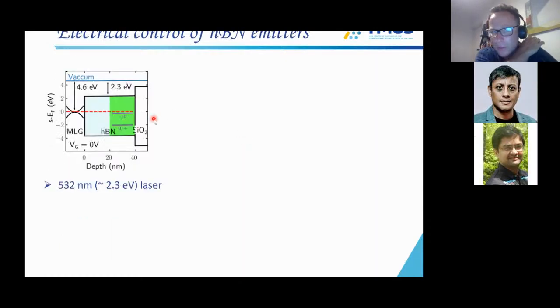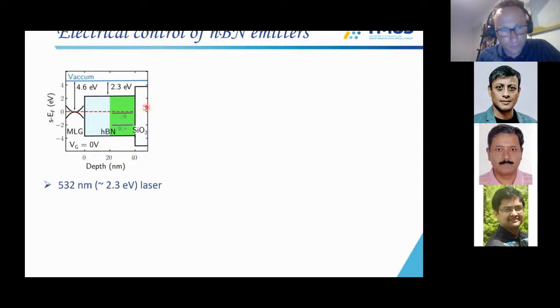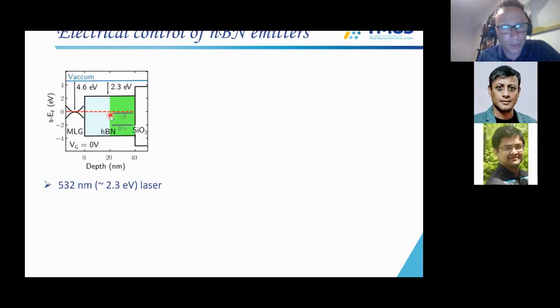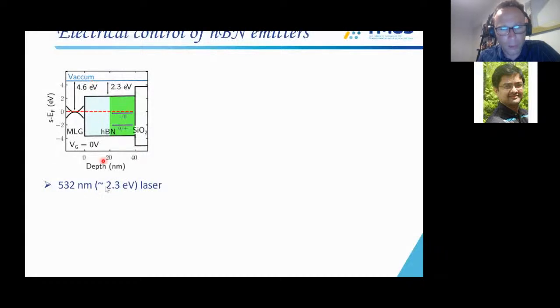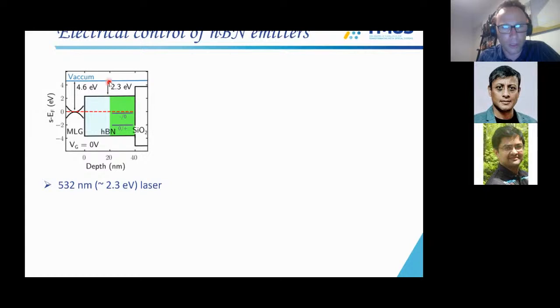a model. And this was with the help of Alistair Stacey and Nicholas Dachuk from Melbourne. What you can assume here is that, again, remember we have an hBN defect with our emitters, and then a cap layer and then a graphene on top. So our emitters are lying somewhere here below the Fermi level of the system, and the conduction band lies about 2.3 eV below the vacuum level. And remember that we're working only with a green laser, right? So it's 532 nm, which is exactly enough to get to the vacuum state.